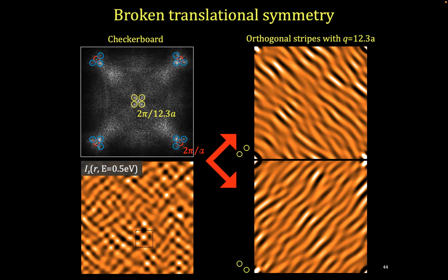So then you take the inverse Fourier transform of that, and you're keeping the phase information from both of these two. This is just the amplitude of this stripe or checkerboard pattern, but you can also extract the phase information of this particular pattern. For example, you can see this wave become like a Y shape, and then split again. So by eye you can already guess there is a topological defect there.